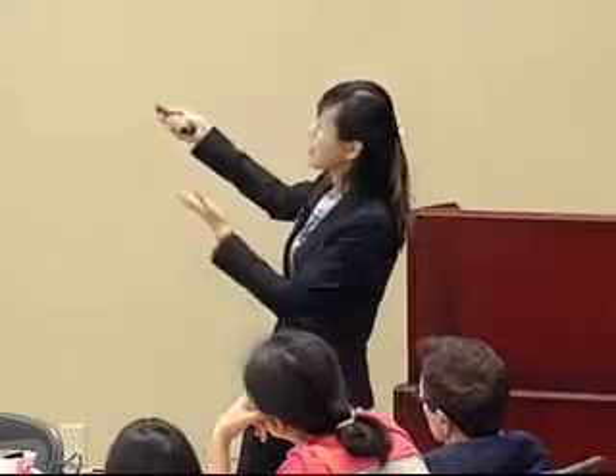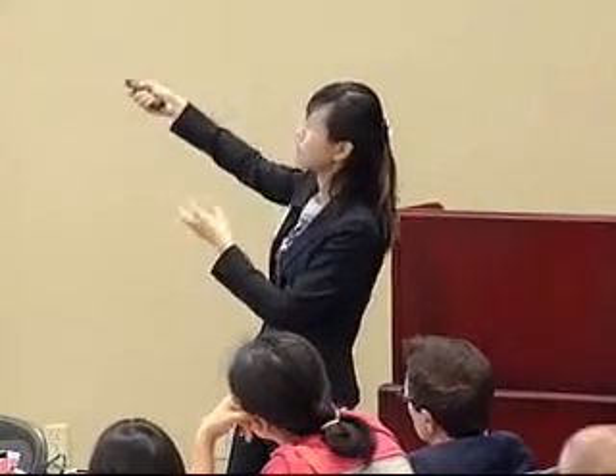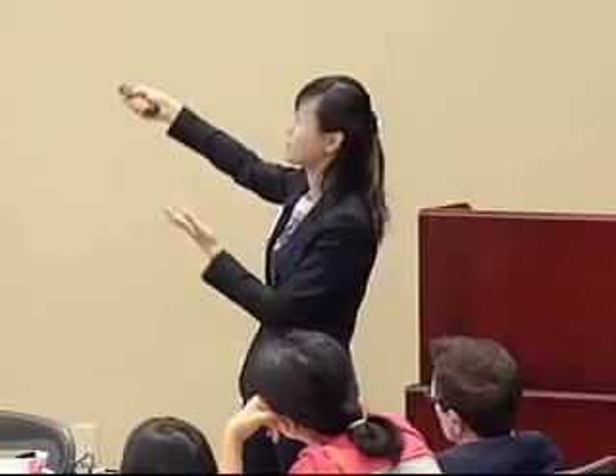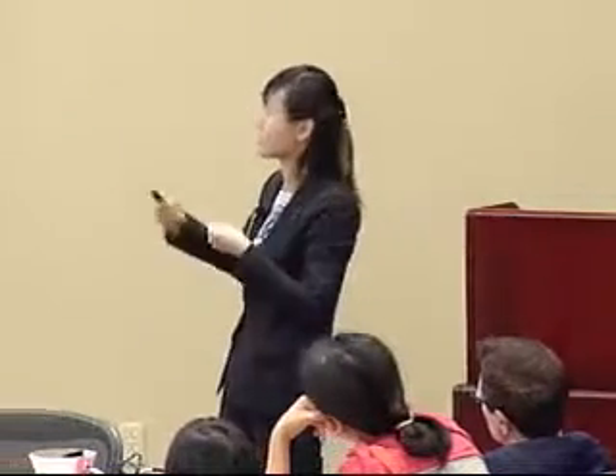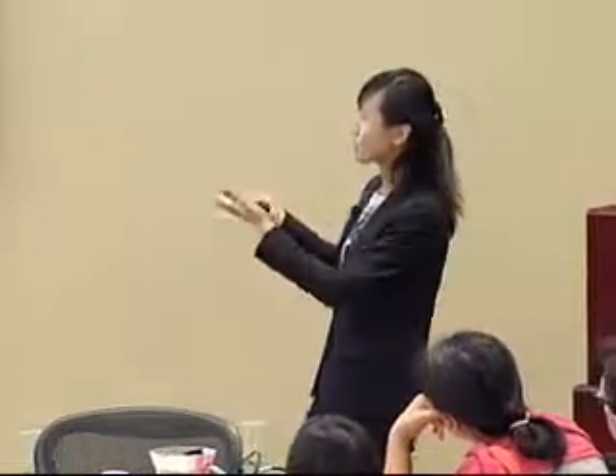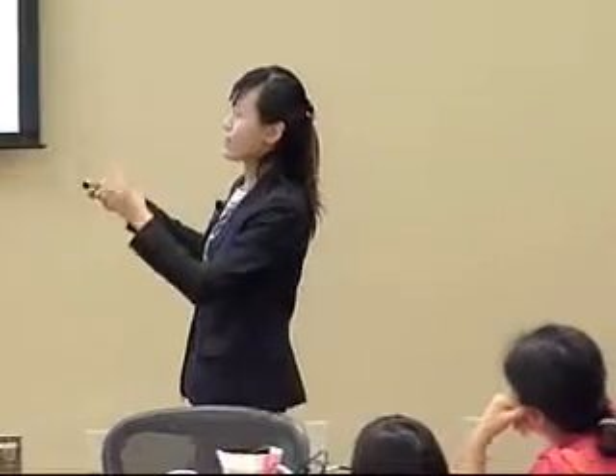And in terms of the stretchability, I tested just about 30% because by all means our skin will start to have failure after 20% strain if we stretch the skin. Even if one day I want to do facelift, I know my limit. So in this case, the intrinsic strain, again, interatomic distance change, is only about 0.15%, far below the fracture or yield strain of our inorganic materials, even after 30% overall strain.